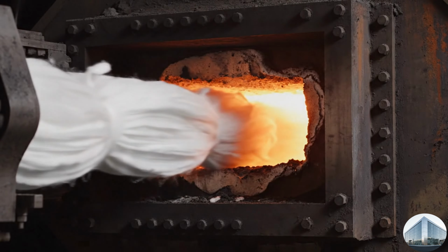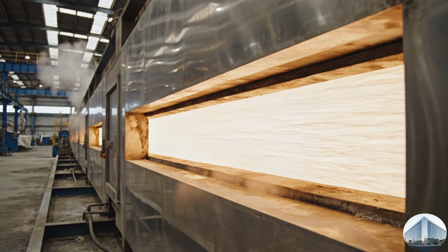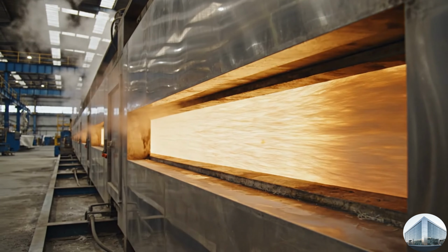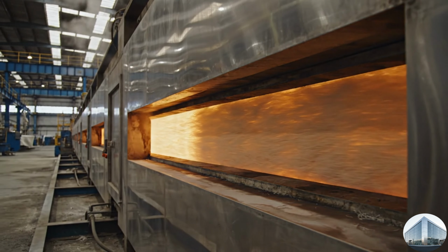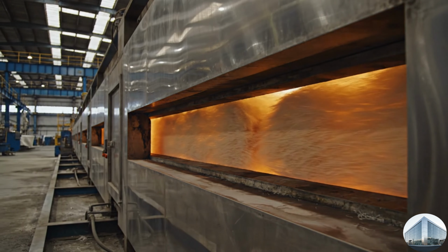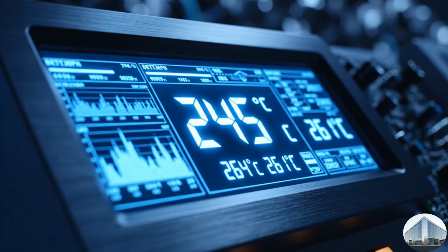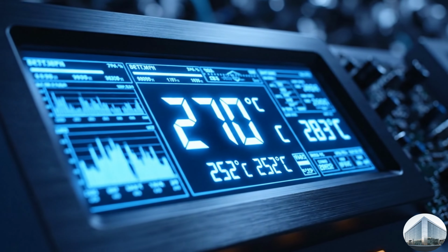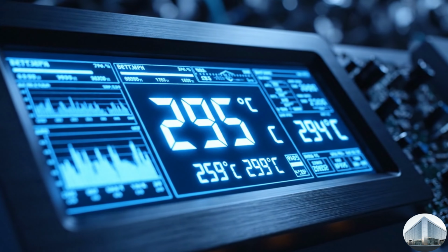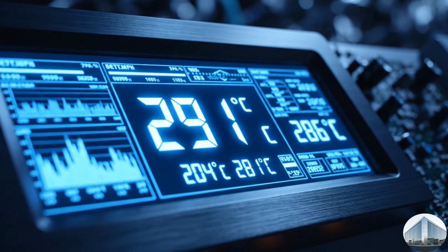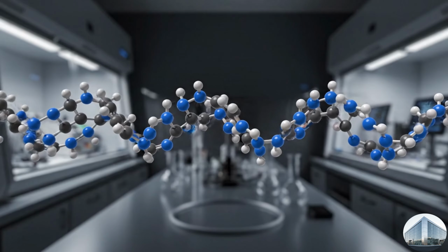Oxidation is the first critical transformation. Under strictly controlled temperatures, the PAN fibers begin to react with the air, changing their color and internal chemical bonding structure. The temperature is managed with extreme precision. Even a few degrees of deviation could ruin the entire batch, as the molecules must reorganize themselves at a specific thermal rate. Inside the fibers, a microscopic dance occurs.